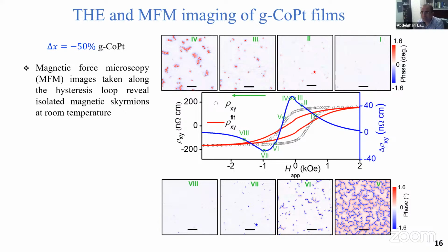Here I show, for example, points 1, 2, 3, 4, 5. The farther away from the topological Hall effect peaks, you see nothing. Then there is creation of isolated spin textures, and then the density starts to increase until you form a labyrinth structure at zero applied magnetic field, or even low magnetic field. And then this is the opposite side.